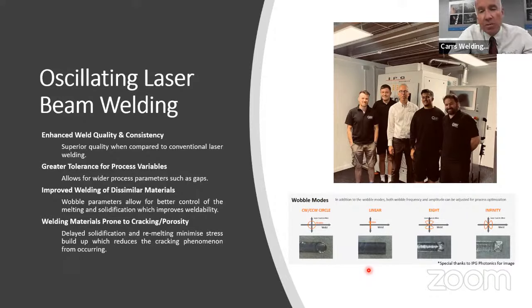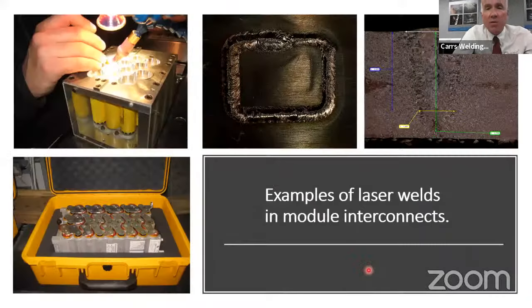The oscillating beam is at hundreds of hertz, and it really does give you a nice looking weld as well as a consistent high quality, and it's brilliant on copper. Paola talked about it: you want a really high quality small spot, single mode if you can get it. We've got a multi-mode, but we've only got the 100 micron fiber here on our system, but it does beautiful welds up to 4 or 5 millimeters deep into copper. Really nice, consistent, low impedance. And so we're working on a few research projects, and can I just talk about a few applications first?